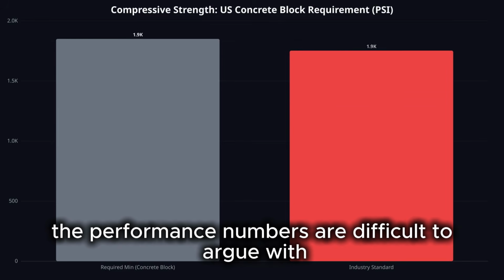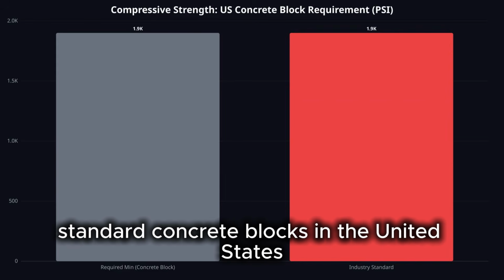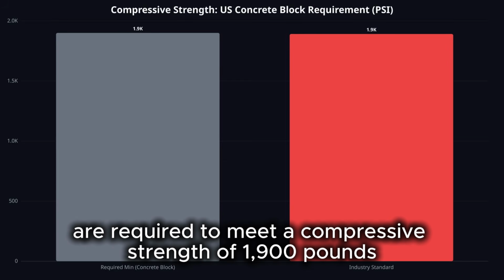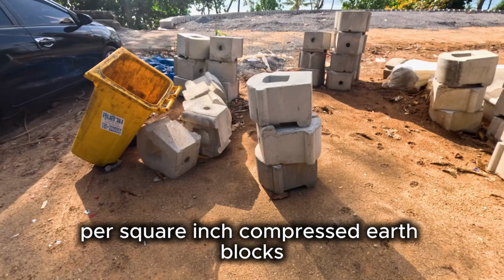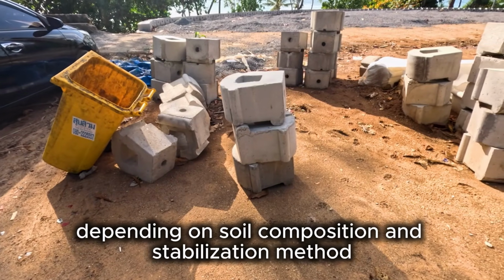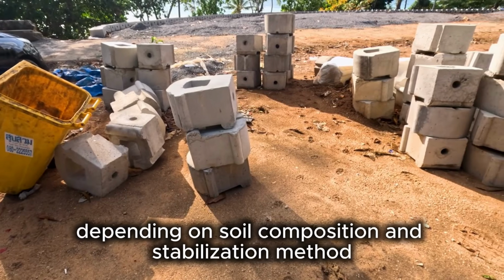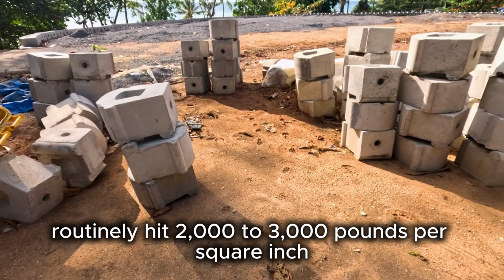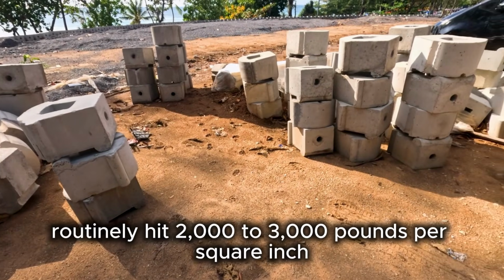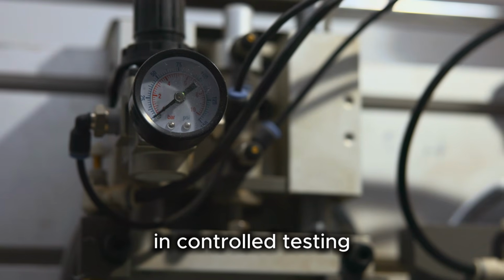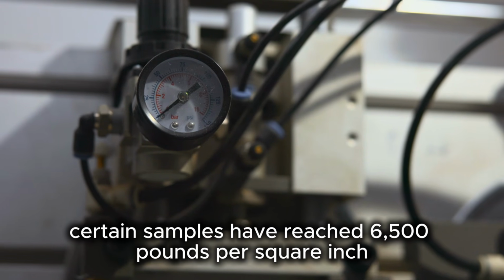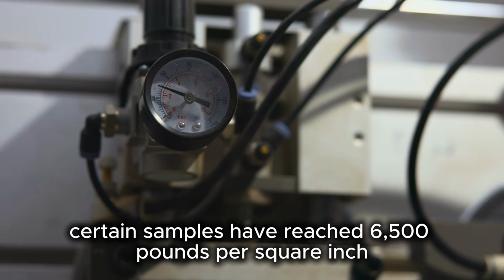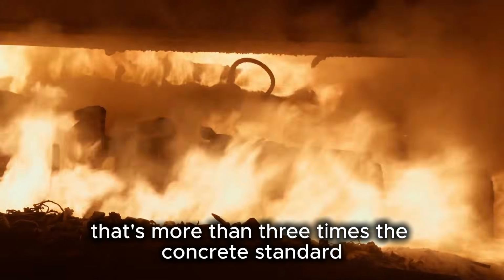The performance numbers are difficult to argue with. Standard concrete blocks in the United States are required to meet a compressive strength of 1,900 pounds per square inch. Compressed earth blocks, depending on soil composition and stabilization method, routinely hit 2,000 to 3,000 pounds per square inch. In controlled testing, certain samples have reached 6,500 pounds per square inch. That's more than 3 times the concrete standard.